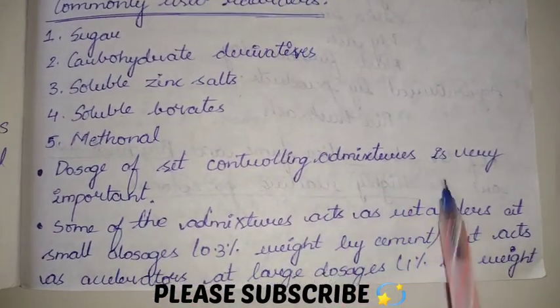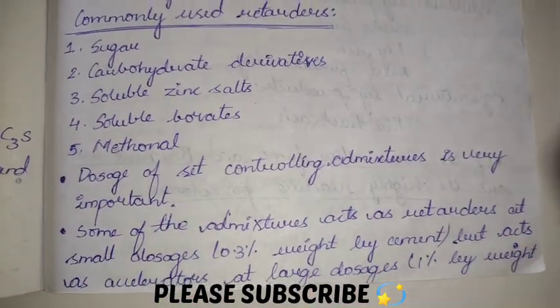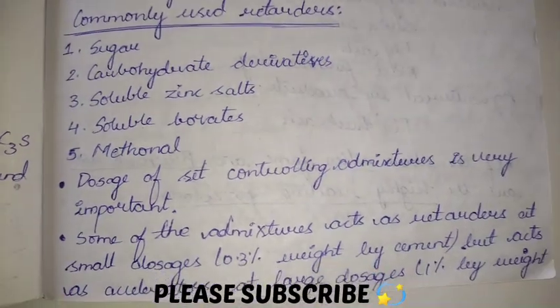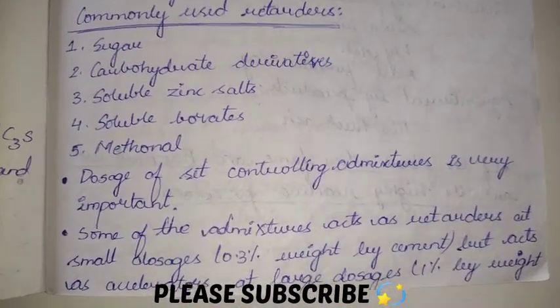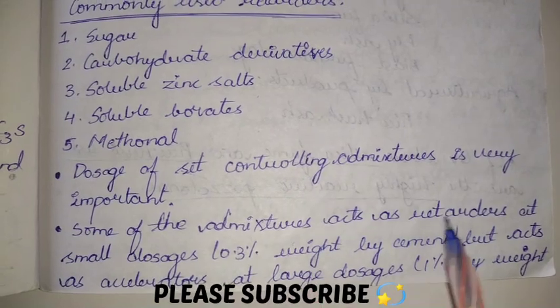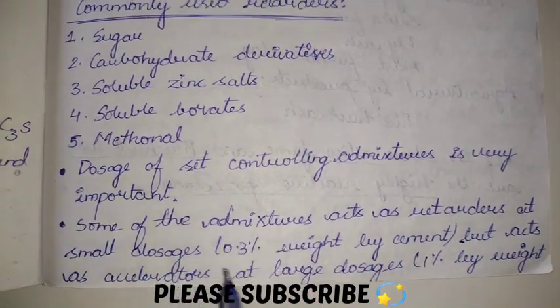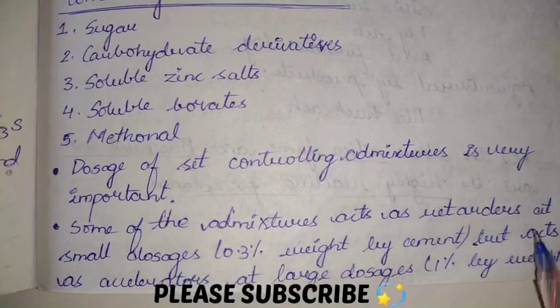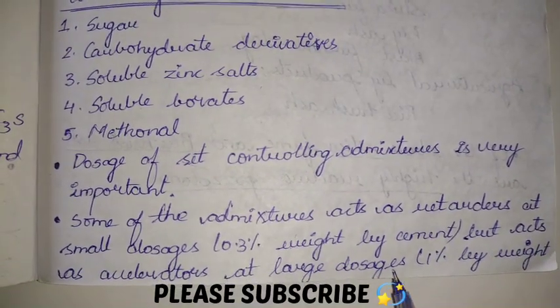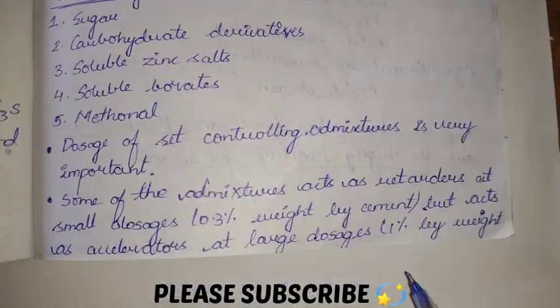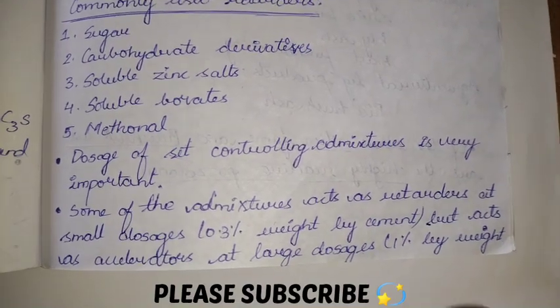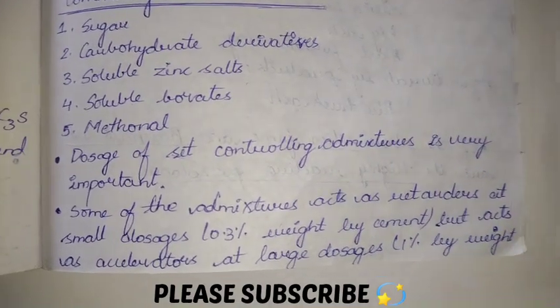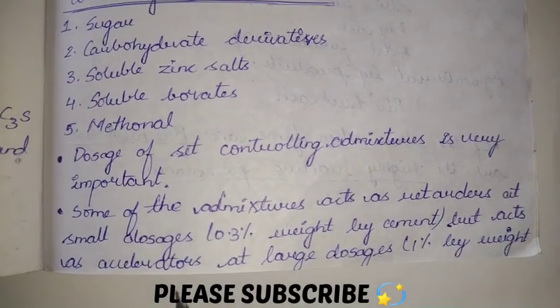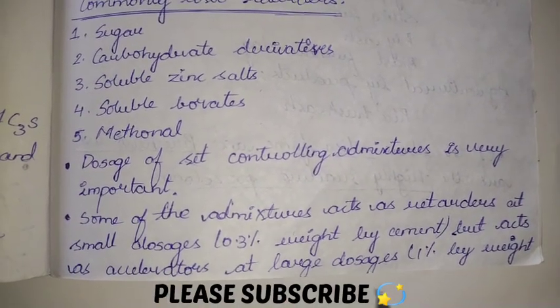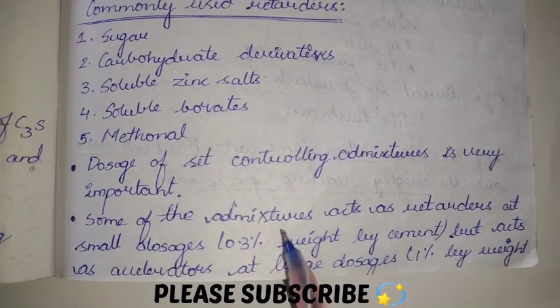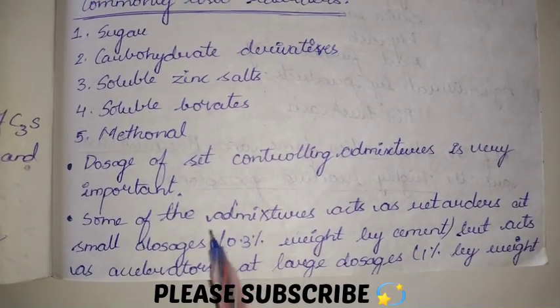Dosage of set controlling admixtures is very important. As I already told you, the quantity, the quality and the timing are very important whenever we are adding these retarders. Some of the admixtures act as retarders at small dosages, like 0.3% by weight of cement, but act as accelerators at large dosages, 1% by weight of cement. So remember, whenever we are adding the retarders, it is very important to check the quantity. And whenever accelerators are used, they are used at large doses. Generally 1%, and here we are using 0.3%.